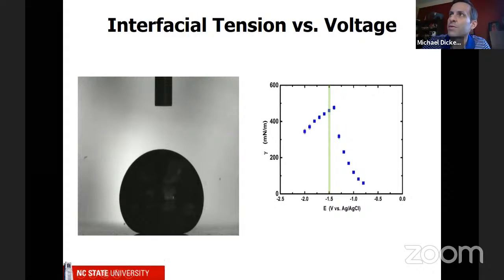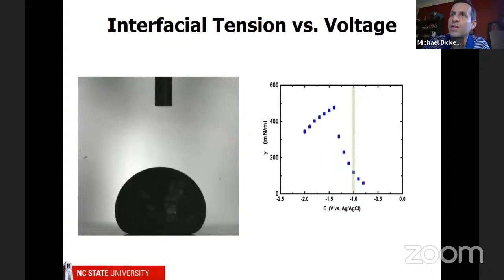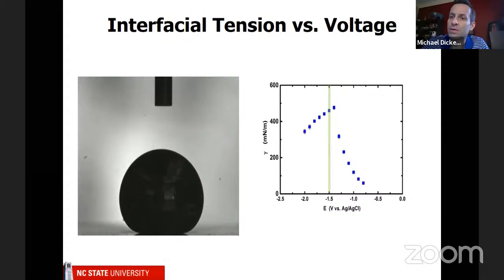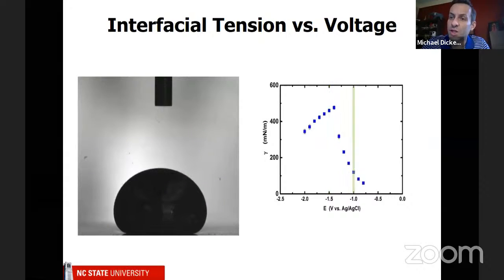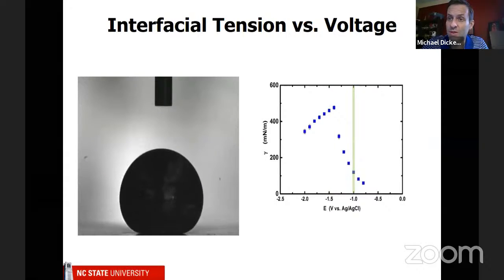So here we go. We're at this large surface tension. We apply a little bit of voltage. The tension goes down. It goes down more. We can go back, completely back and forth. So again, from the shape, we can get the surface tension, which is the y-axis. And by controlling the voltage, we can control the x-axis. So this is completely reversible.